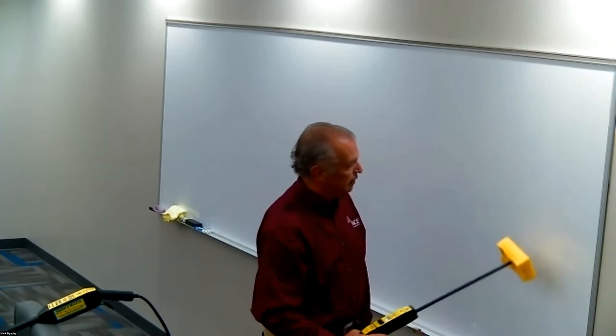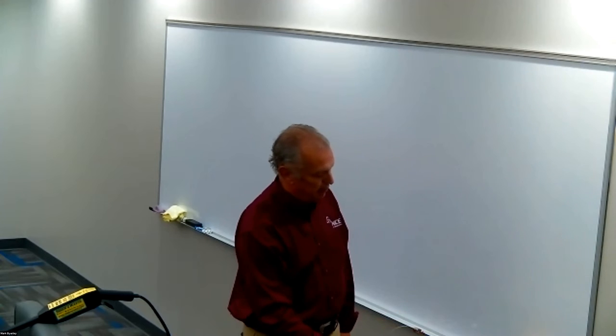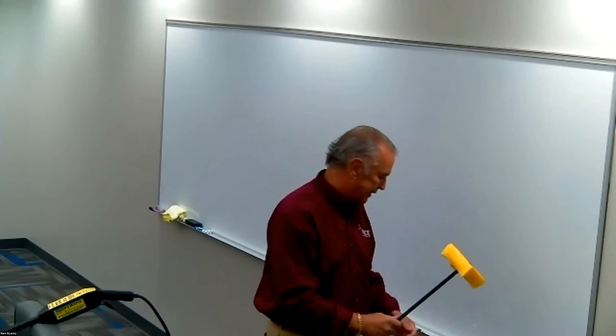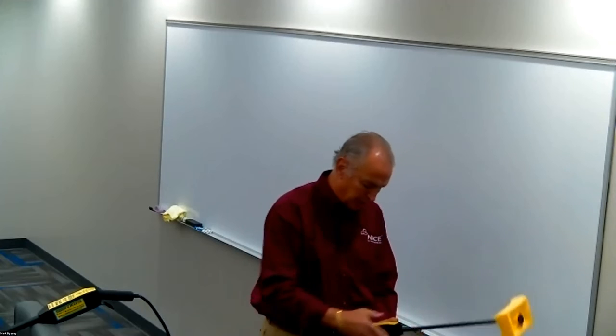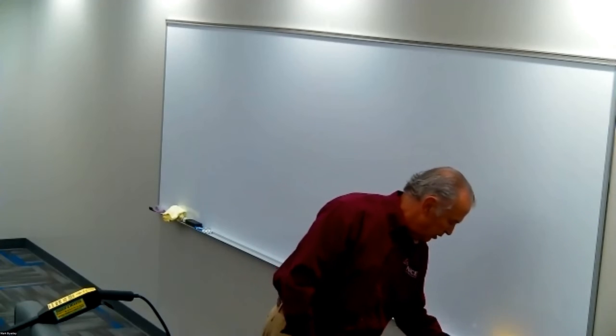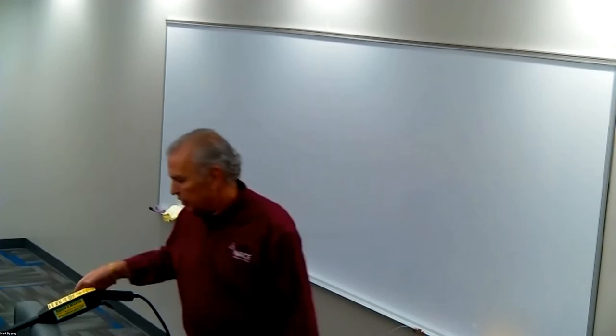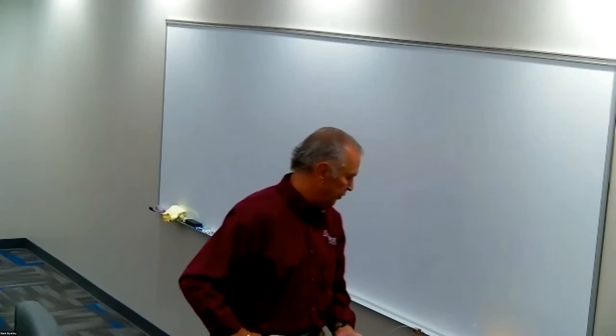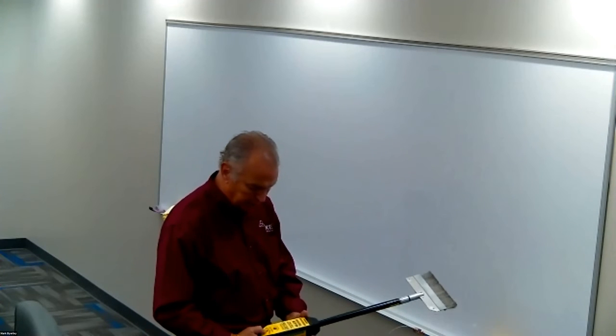So again, non-conductive because it's coated, and then conductive. So that's the fun of wet sponge holiday detectors. Then as far as high voltage goes, and for the gentleman with the hopper question, this is a wire brush, so it allows the wire to move out of the way. So if you've got uneven surfaces, even rough coatings, it'll allow it to go up and over the bumps and bridges, if you will. So what we do is we want to turn the holiday detector on.